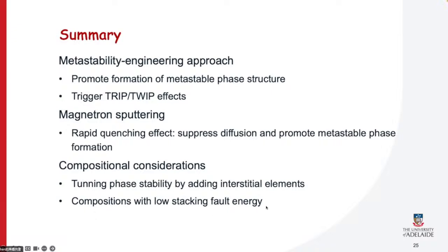And also in the second study, the chromium cobalt nickel one, we picked that composition because it has low stacking fault energy. So we don't need to add any other interstitial elements because the stacking fault energy itself is low enough. So if you want to design something metastable, you need to focus on the phase stability and the stacking fault energy.